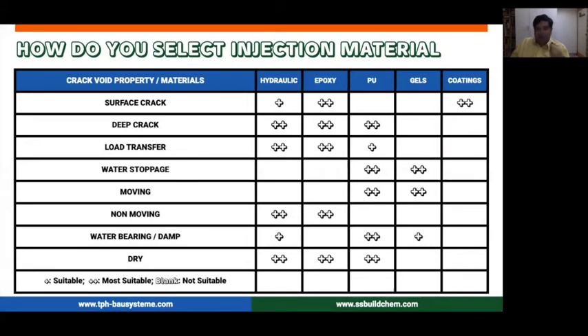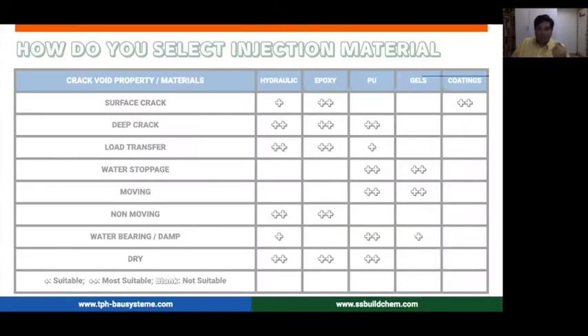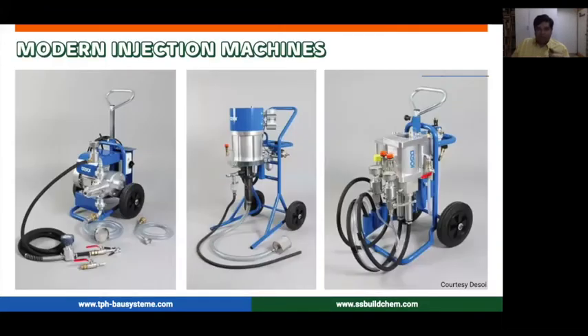There are today certain PUs also available with us, which we call structural PUs. They also reach compressive strengths of almost 70. So in case your voids are a little bit wet, if they are damp, the basic epoxy or cement can run. But if it's a bit wet, then you can also use those kinds of structural PUs to seal those kinds of cracks.